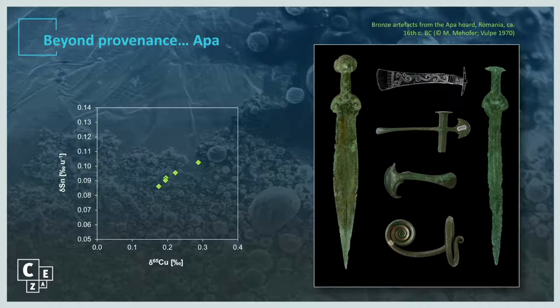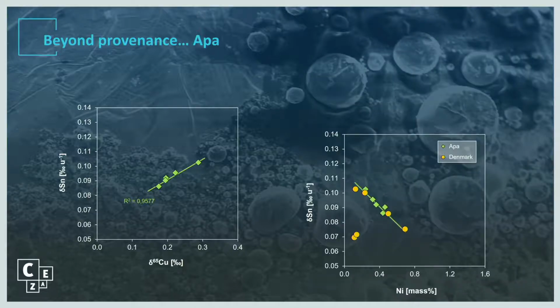And what you can see here in this diagram, and this was very surprising for us, is that we get a very good correlation in copper and tin isotopes. We also get a correlation between the tin isotope composition and, in this case, the nickel concentration, and the copper isotopes also correlate with the trace elemental data. This is a very good indication that we are faced here with some kind of mixing of bronzes, because if you wouldn't have mixed bronzes, we wouldn't get such a correlation in tin and copper isotopes.